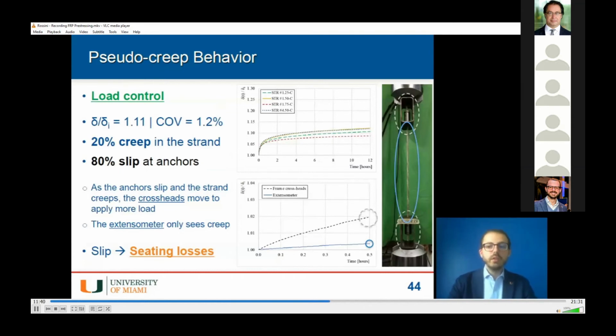In order to verify this possibility, we conducted some pseudo-creep tests. Why do we call it pseudo-creep? Because the displacement that you see in the diagram on the right is not only caused by the inherent material-based creep of our GFRP strand, it is mostly caused by slipping and by phenomena that are localized and happening at the anchor location.